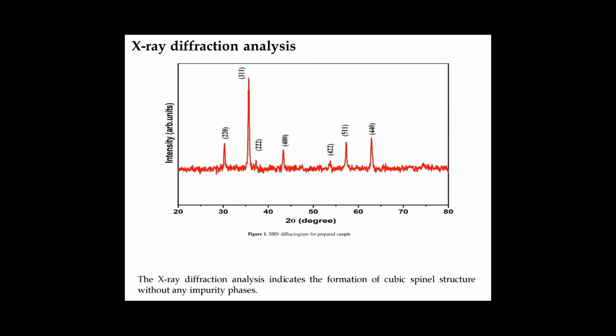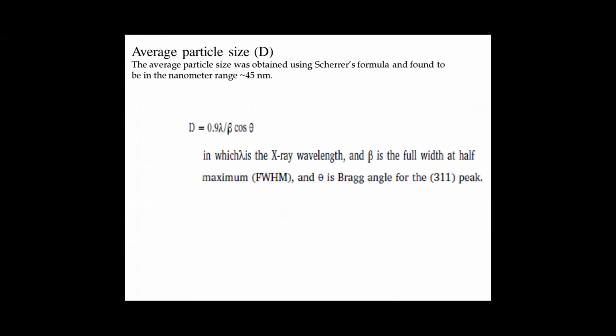The X-ray diffraction analysis indicate the formation of cubic spinel structure without any impurity phase. Average particle size we have calculated from the Scherrer's formula. The average found to be in nanometer range, 45 nanometer.